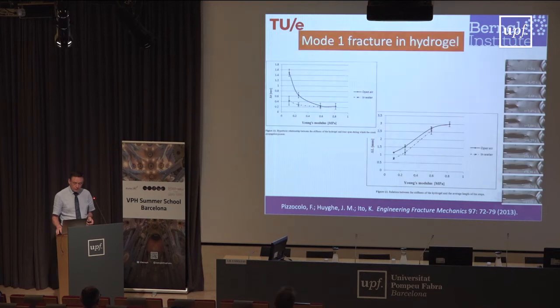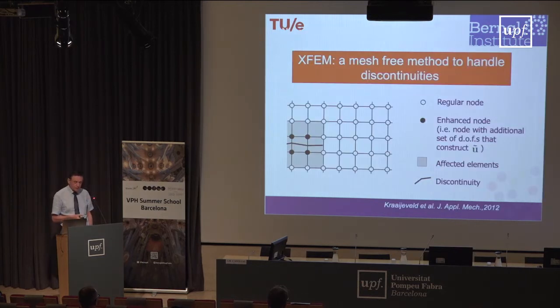And so we also could show that the distance between the teeth depends on the Young's modulus. We did many, many of these experiments, and you see that as Young's modulus increases, you get a longer distance that it propagates each time between the steps. And the time it pauses does the opposite. It is higher for low Young's modulus and lower for high Young's modulus. So, interesting finding, but we tried also to simulate this. And you say, well, we use XFEM. XFEM is an advanced method of finite elements, well known, to do fracture propagation.